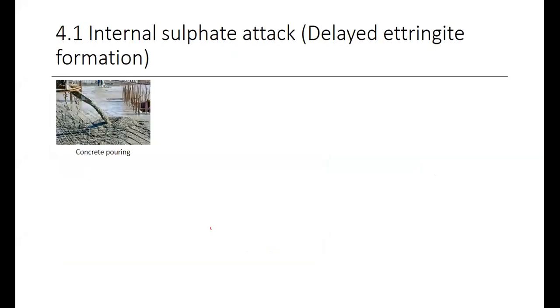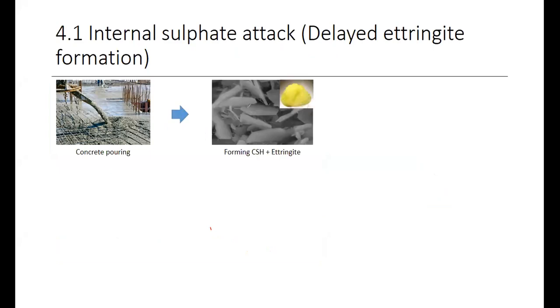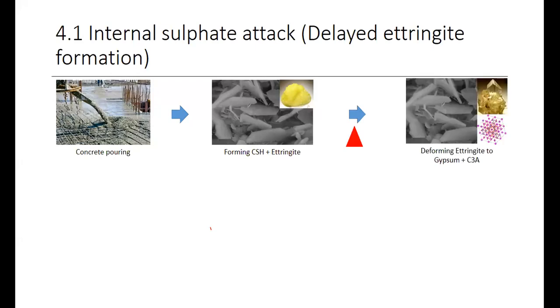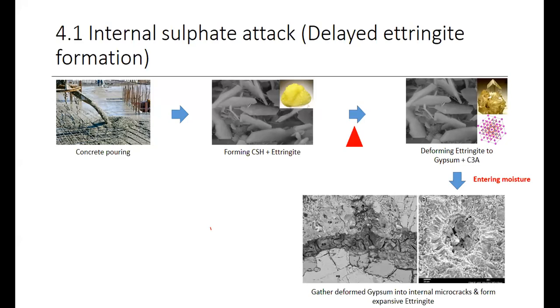Before that, we'll discuss what delayed ettringite is. We already know what ettringite is. Initially, with the reaction of cement, C-S-H forms, as C2S and C3S form C-S-H, and C3A reacting with SO3 will produce ettringite. We already discussed that matter. But with a high amount of heat or thermal forces, this ettringite decomposes back to gypsum and C3A. It decomposes back because it's not stable at higher temperatures. In the presence of moisture, and this is very important, it will react again, because moisture creates the required reaction media, and again it will form ettringite.